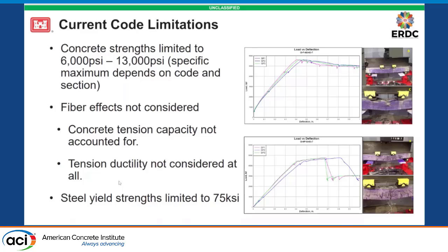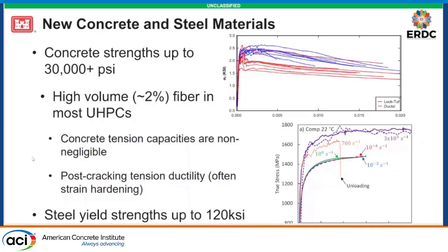So these new materials, as I mentioned, may have significantly higher strengths, also significantly higher volumes of fiber. And the tension capacities can be quite significant. The upper right-hand graph shows some different UHPCs, one that we developed in-house at ERDC, and another, Ductal, which is a commercially available product by Lafarge-Holcim. Based on a direct tension test, we're seeing strengths between 1.5 and 2.5 KSI. So this is where we're getting direct tension strengths that are approaching the range of what we think of as the minimum level of compression strength for concretes. And that certainly can be factored into design very beneficially.